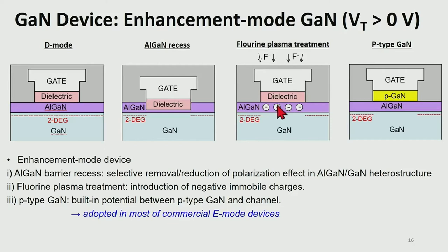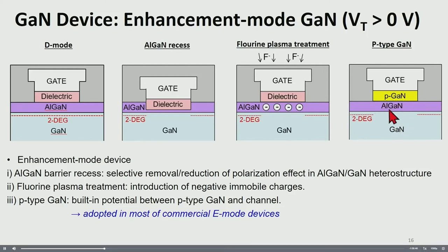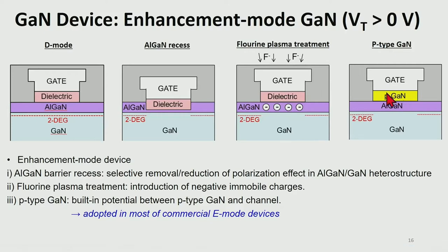Also, there is some concern about the stability of the implanted fluorine ions during high temperature processes or long-term operation. The last approach is the pGaN on top of the AlGaN barrier. If you grow the pGaN on top of the AlGaN barrier, the entire gate structure is like a PN junction. So the built-in potential difference between the pGaN and the N-type channel can raise the band and it depletes the 2DEG channel under the gate. Since the pGaN growth is done during the epigrowth, this approach can have better threshold voltage controllability compared to the other approaches. And until now, this approach is winning. Most commercial enhancement mode devices use this pGaN gate structure.